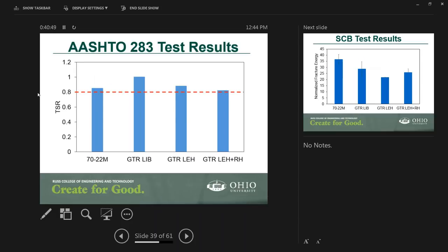So TSR for all mixes, whether it is the polymer modified or GTR, and again, those tests are on core samples obtained after construction of the test sections. We have seen that the TSR values, which is an indicator of the resistance to moisture damage, in all cases were higher than 0.8, which is acceptable, and similar to the polymer modified.